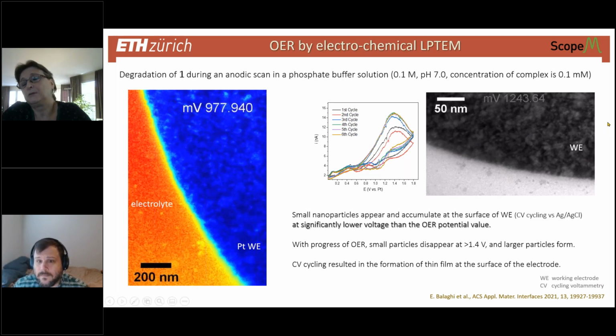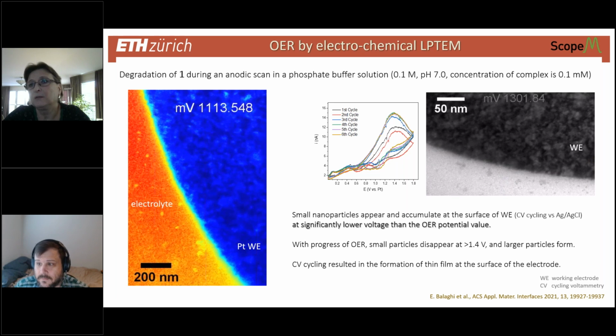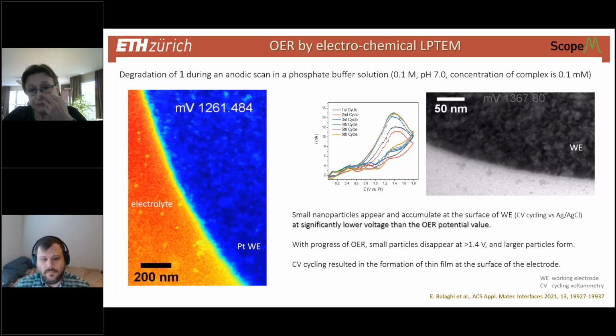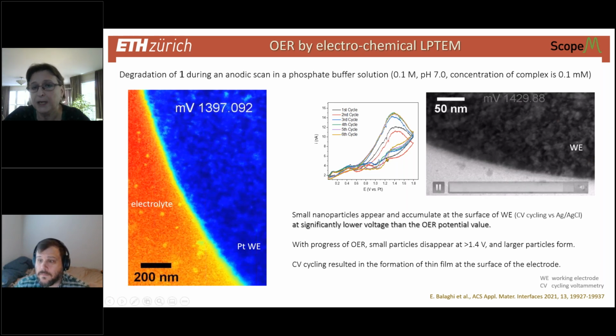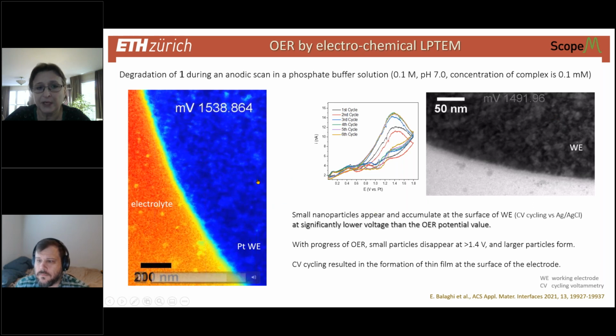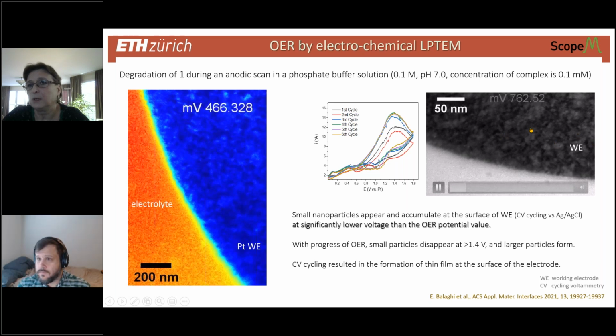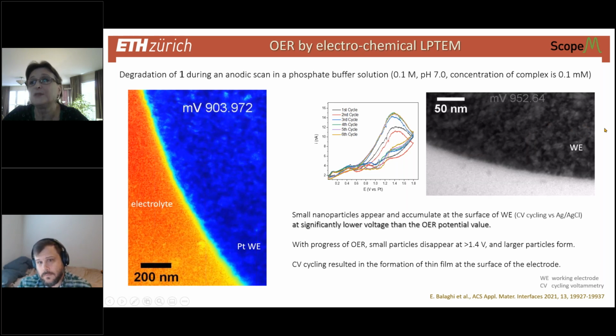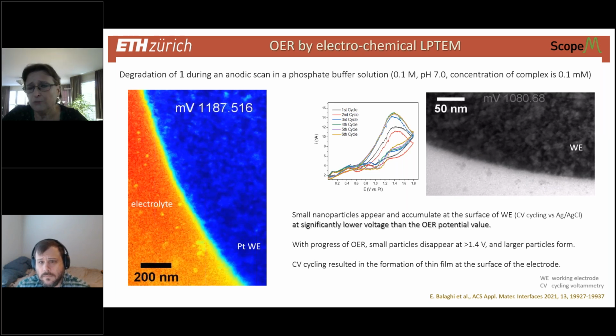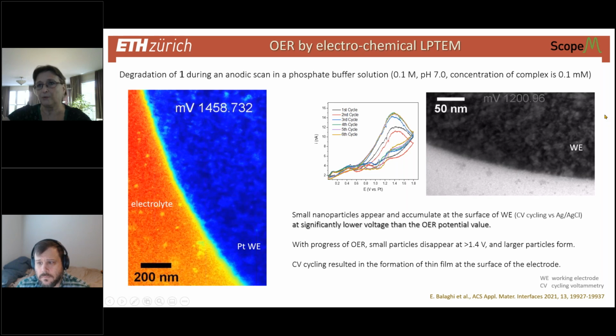You're actually asking a quite valid physical question of the nucleation or precipitation. That's why I included two different electrodes. This is platinum, a crystalline electrode, and this was a glassy carbon electrode, so it was amorphous. It is very difficult to find it in view without an objective aperture, which limits the field. You cannot even image it before the reaction started.